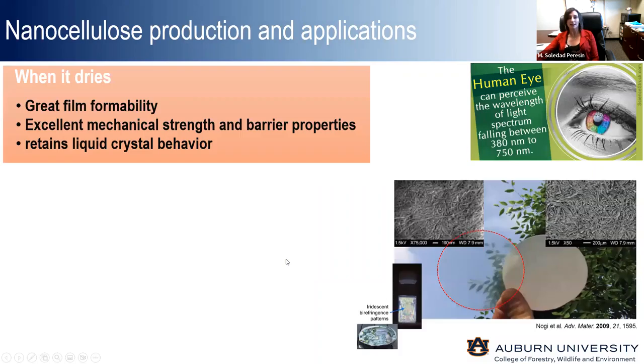So what we can see is that nanocellulose has a very good film formability, particularly if we are talking about very small fibril size. We can have at least translucent or transparent films. Here in this slide, you can see a piece of paper that is opaque, but also a nanofibrillated cellulose film that is fully transparent. And this is nothing more than caused by the size of the fibrils, which we cannot really distinguish with our bare eye, and the disruption of the light.